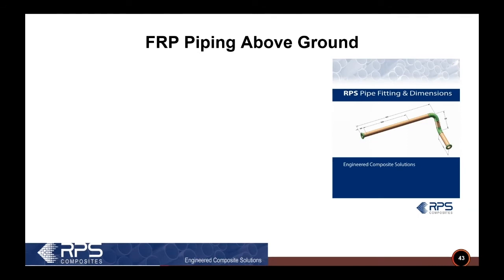When it comes to the actual dimensions of FRP pipe, FRP is generally speaking all based on the ID. You saw the person laying up the T. Well, they start out with a T mold that's 3.0, and they apply reinforcement, and the finished is 3.41 or some strange number. So everything has a fixed ID, and then the OD is going to vary by the component, the liner thickness, the pressure rating, all that sort of thing.